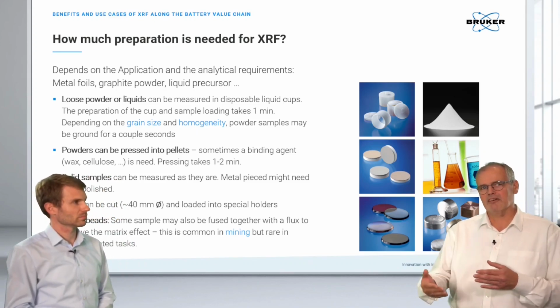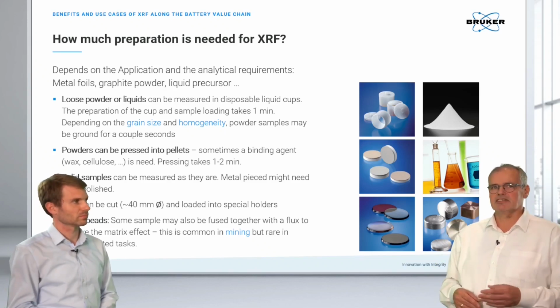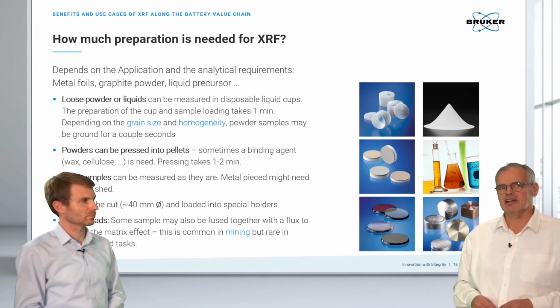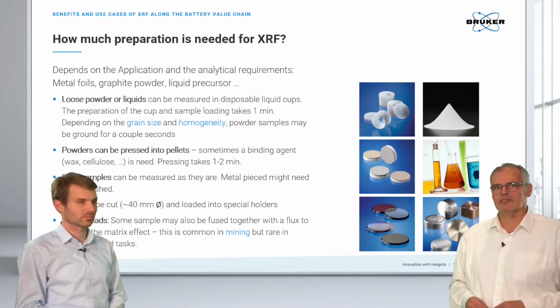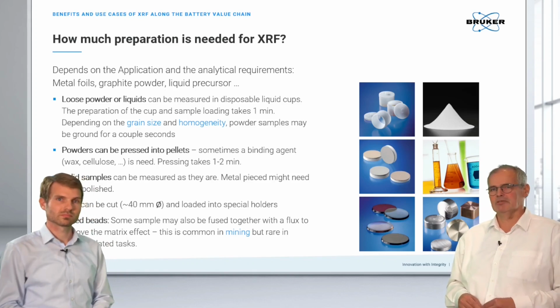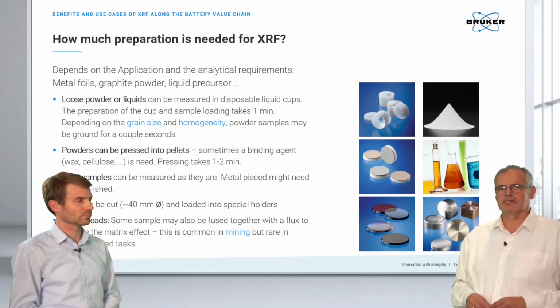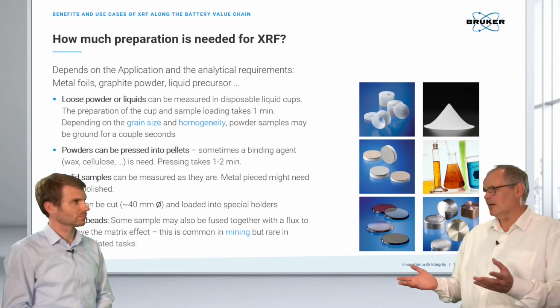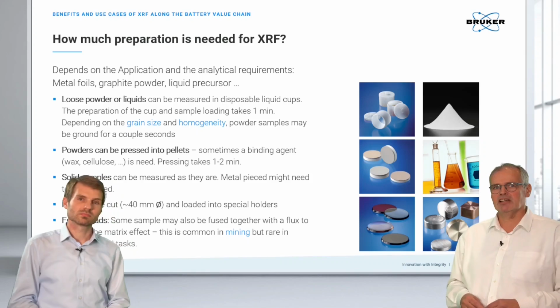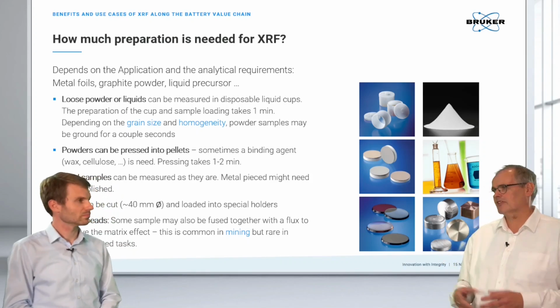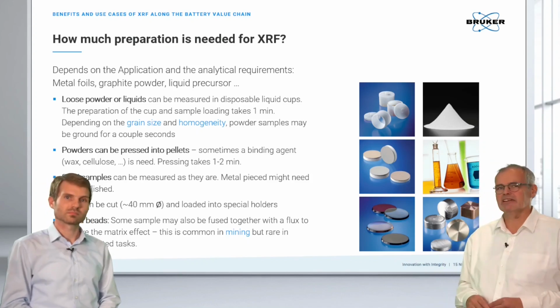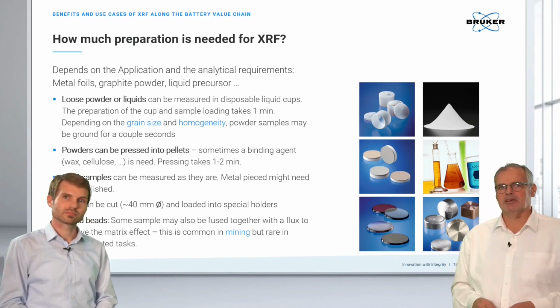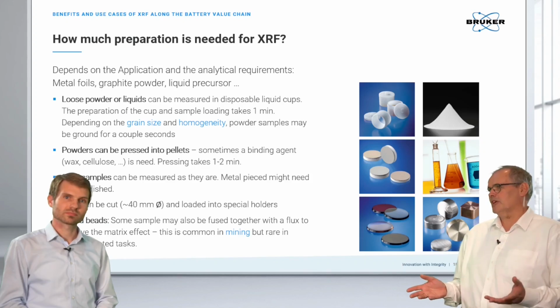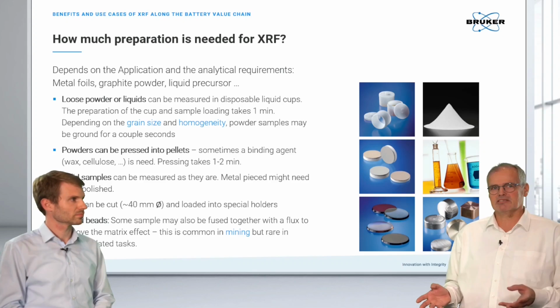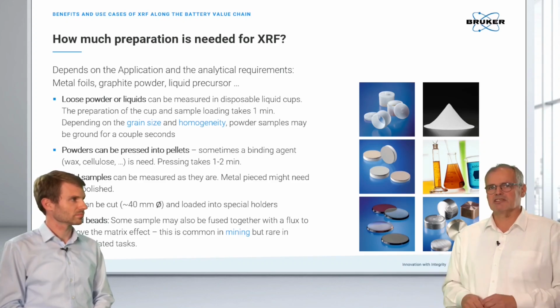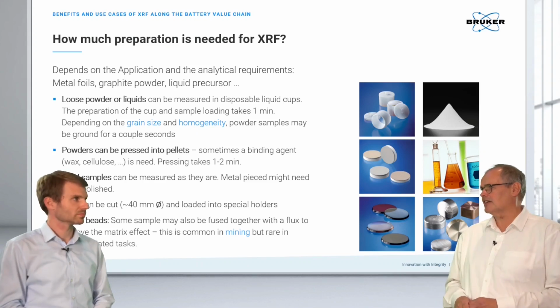If we want to have a little bit higher intensity and sensitivity, if we want to be more representative with the sample, we press the powder with a little bit of binder after grinding into a stable pellet. Those can be stored also for years. Nevertheless, solid samples we can cut into shape and analyze directly. Sometimes we need a little bit of polishing. Think about a coated metal sample or a painted metal sample. We need to see the bare metal. That's it. Foils, quite interesting, can be analyzed directly. That means take one of the liquid cups, use this liquid cup to stretch the foil and then analyze it directly.